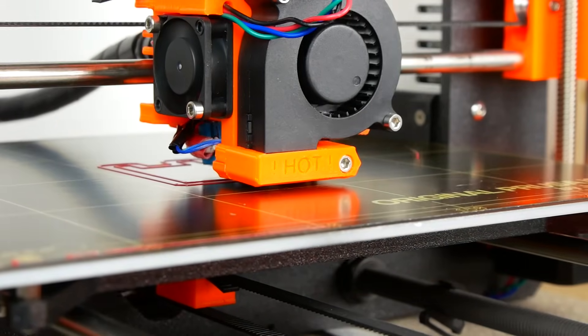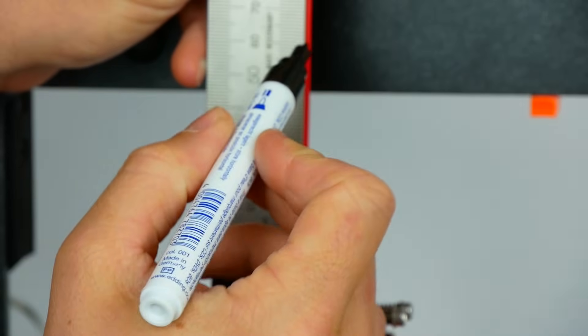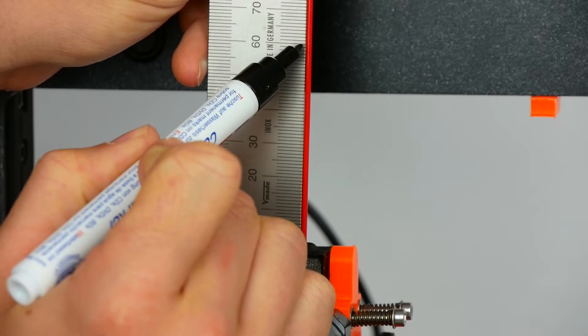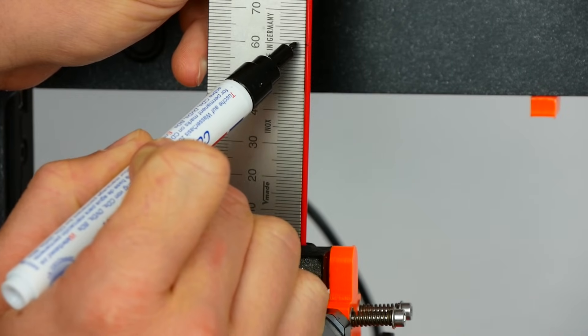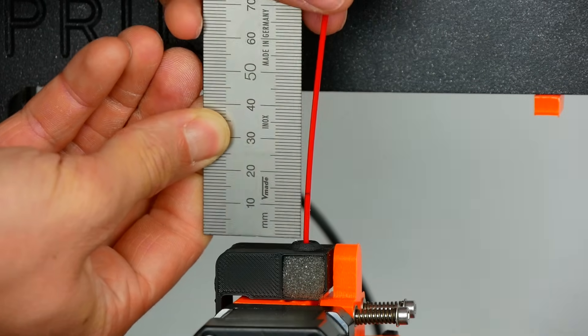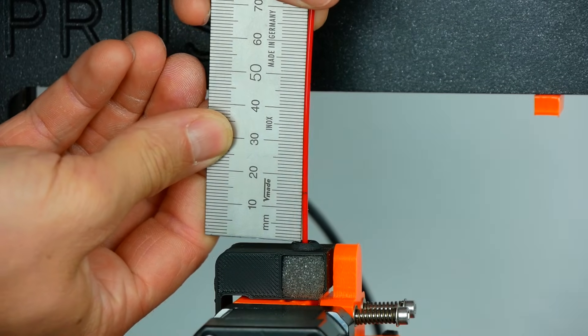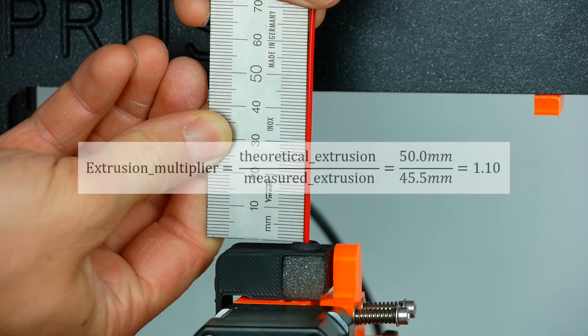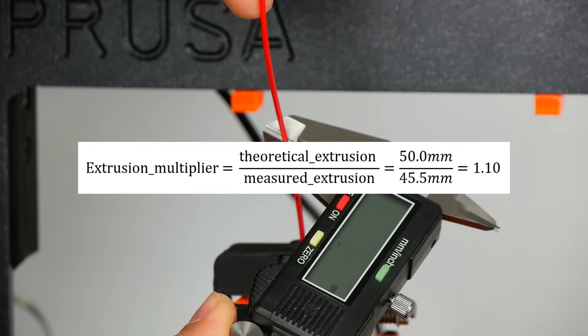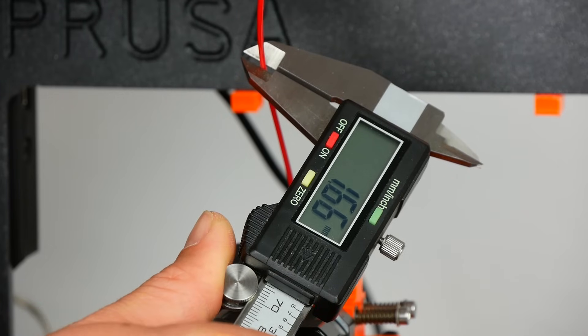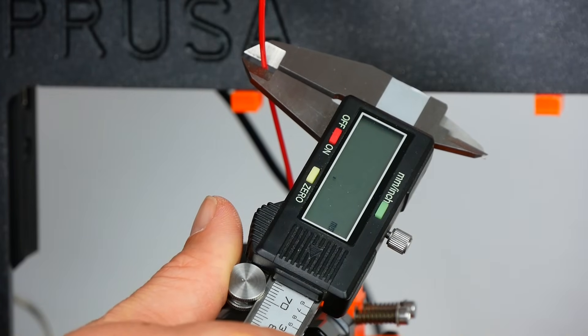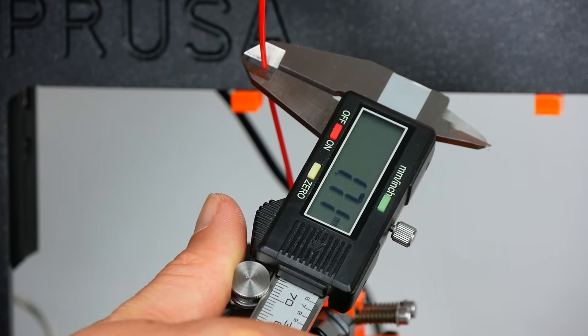This is done quite simple. I mark a given length, for example 60mm on my filament, then I use any interface software like Octoprint or PronterFace to extrude a slightly smaller amount of filament, here 50mm. Make sure that the extrusion speed is not too high because this could screw up your results. After the extrusion is finished, measure by what amount your filament was moved. By dividing the desired extrusion by the real extrusion, you will get your extrusion multiplier.